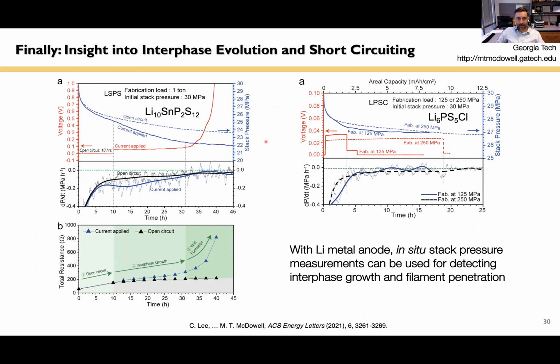And finally, I'll just say there's this paper we're also quite excited about that came out about a month ago, where we use similar stack pressure measurements, but instead of investigating alloys, we investigate lithium interfacial behavior. So we examined the differences between interphase formation in an unstable system and filament formation in a stable system. And we're able to detect differences in the signatures of stack pressure due to interphase formation and lithium filament growth. So check this out if you're interested. The citation is down here.